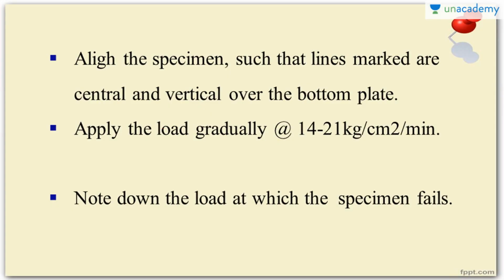Now, after this, apply the load gradually at the rate of 14 to 21 kilogram per centimeter square per minute. Apply the load gradually and see at which point the split happens or the specimen fails. Then release the load. So that's how we perform this test.